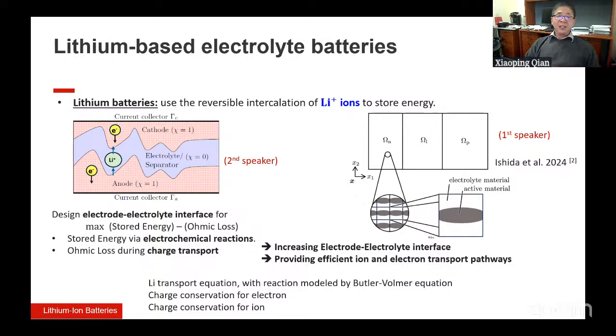So here, in the battery, we want to maximize stored energy and reduce the ohmic loss. The energy is actually a function of species concentration or concentration gradient. It also depends on the electrical or ionic potential. That is governed by the PDE, the lithium transport equation, where the electrochemical reaction model is given by the Butler-Volmer equation. For the electric potential or ionic potential, we have the charge equation. So within this PDE, essentially we can maximize stored energy and reduce ohmic loss.